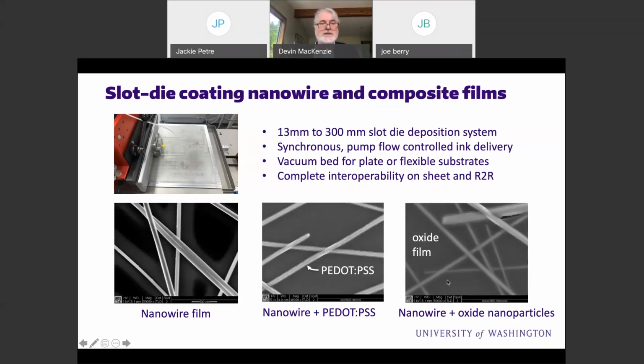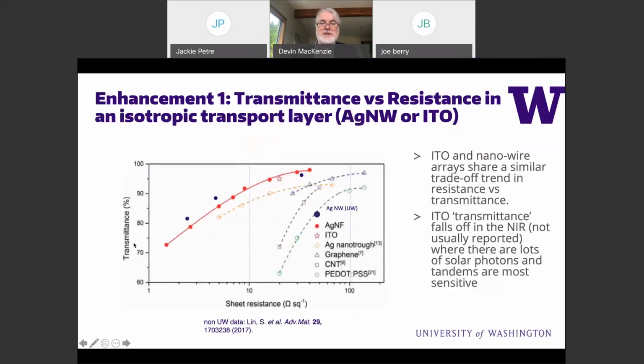Embed those in the slot-die coating. It's a continuous solution of PEDOT, continuously, and we get some quite good results versus ITO. And this is all done at very low temperature, 70 degrees C max drying, and you could probably develop it lower than that.